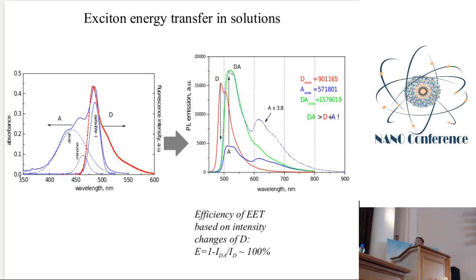In addition, we can observe that the shape of the enhanced emission is different from the neat photoluminescence of acceptor J aggregates. That means that something happens in solution when we add donor molecules to the acceptor J aggregates. Something happens in the solution.